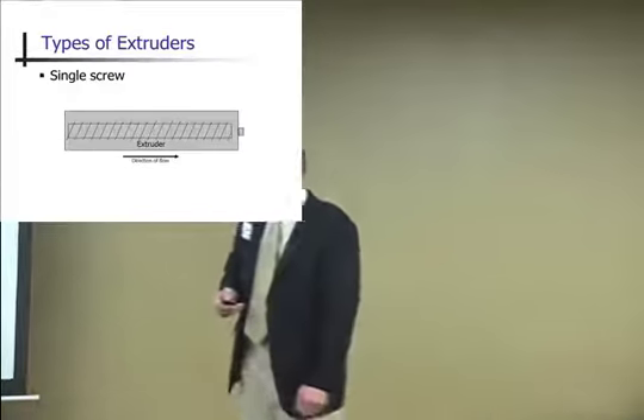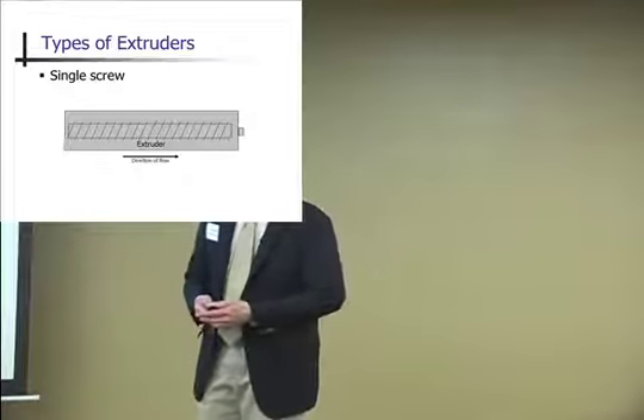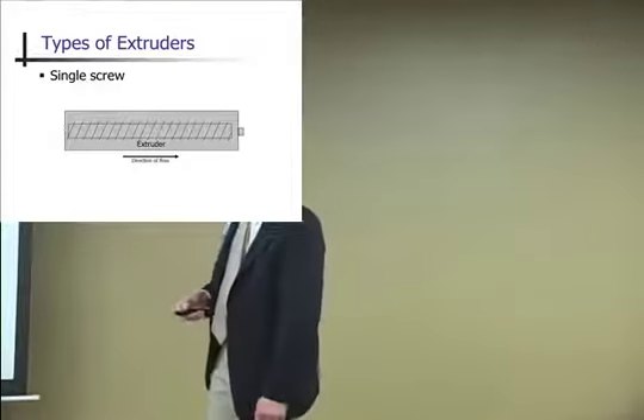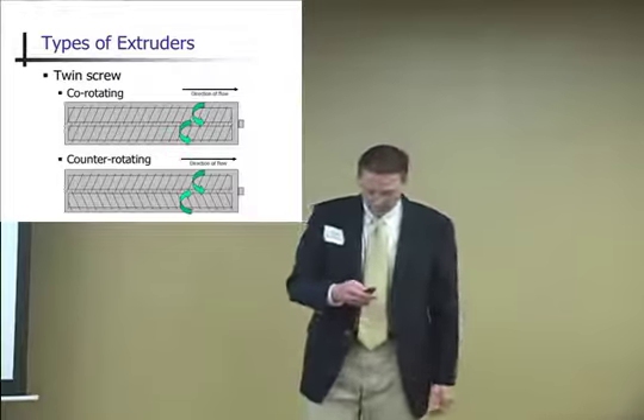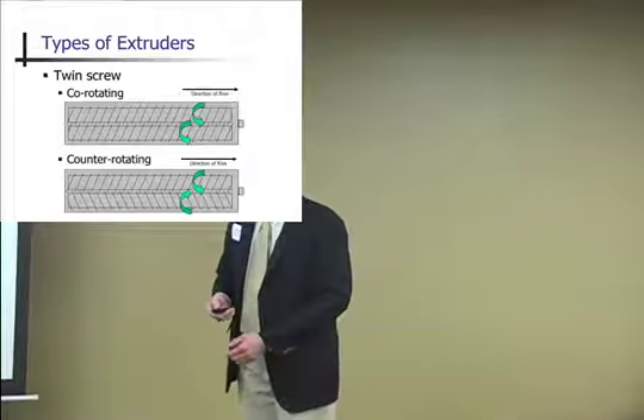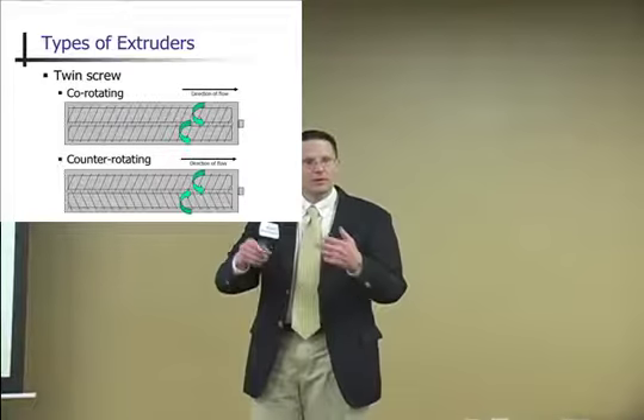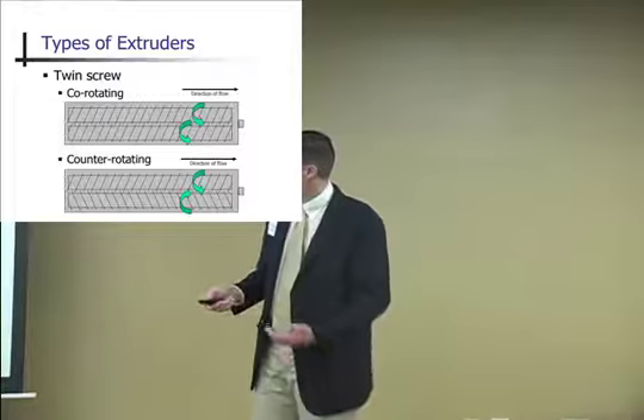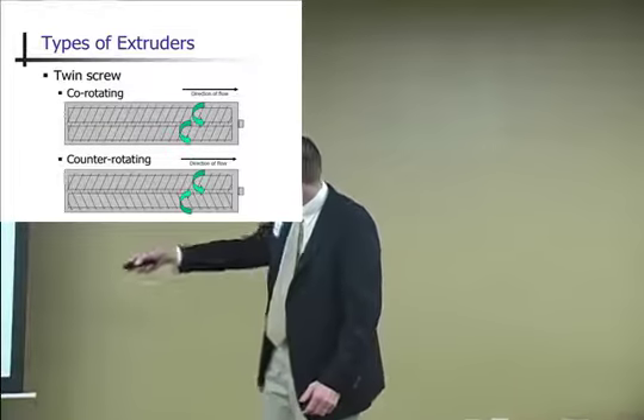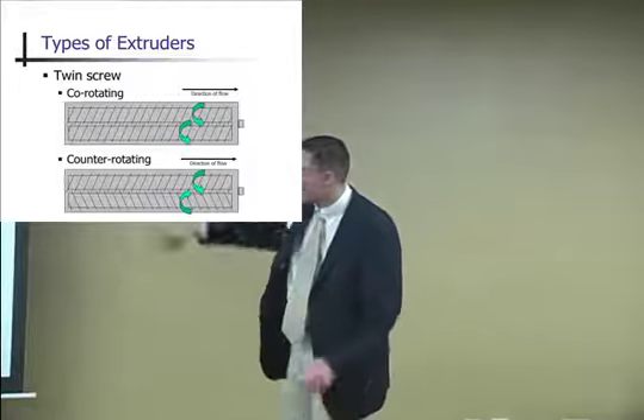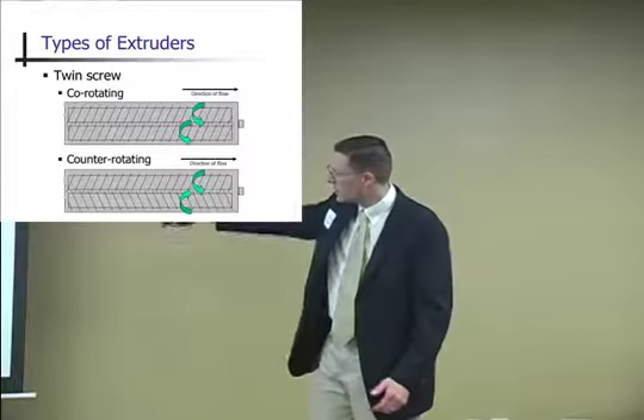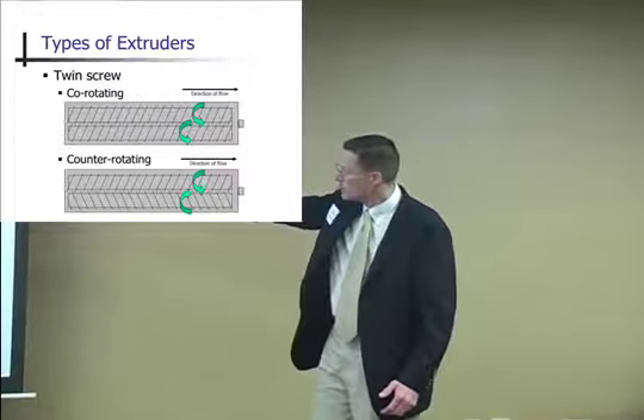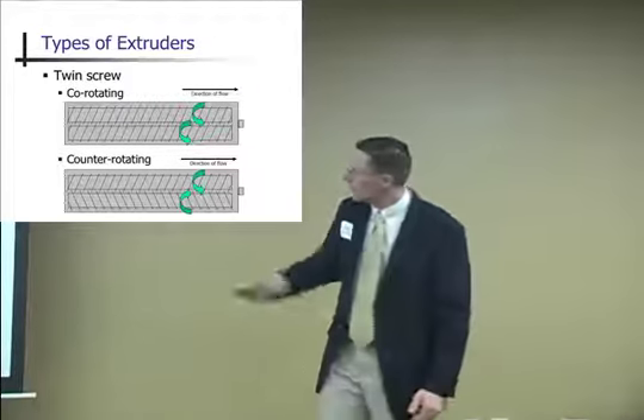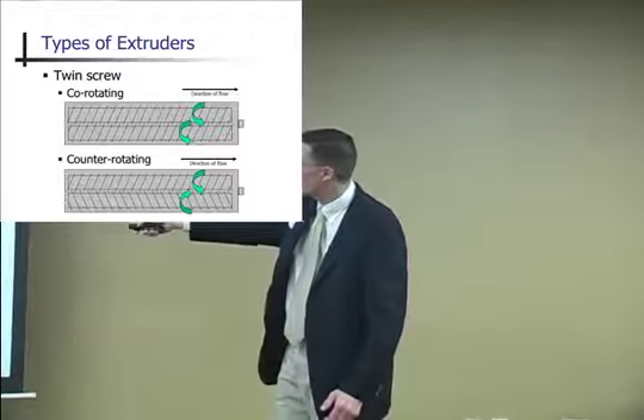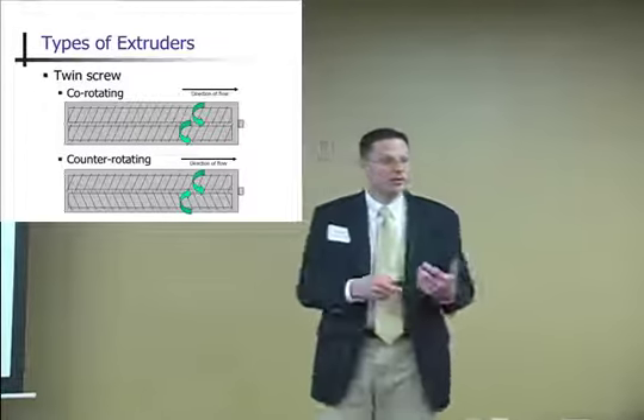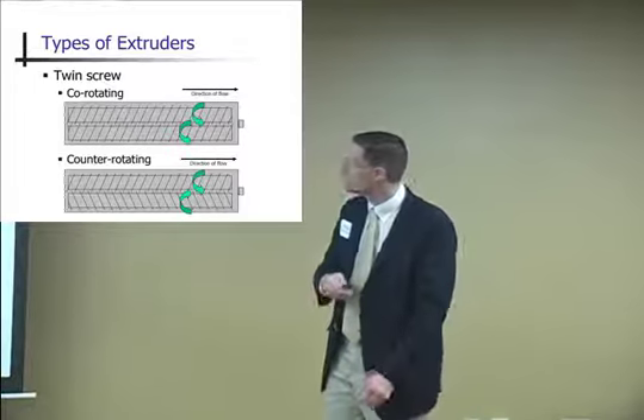So a common type of extruder is the single screw. But there's also twin screw extruders that are available. Now, if you have a twin screw extruder, the screws can be rotating together or rotating opposite of each other. What's the advantage? This type of extruder, the counter-rotating, actually gives you better mixing capabilities because those ingredients are pushed into the opening, into that space between the screws. This type, where you have them rotating in the same direction, does a better job of conveying, but not so much in terms of mixing.